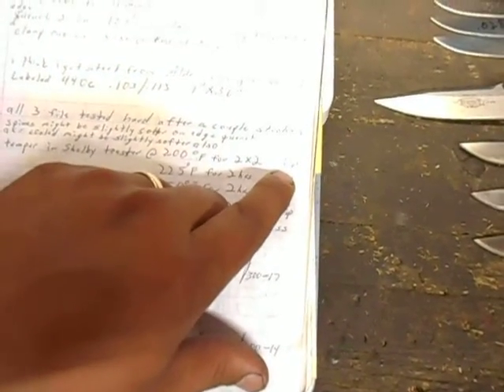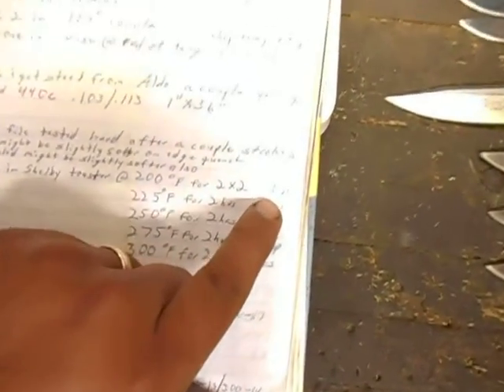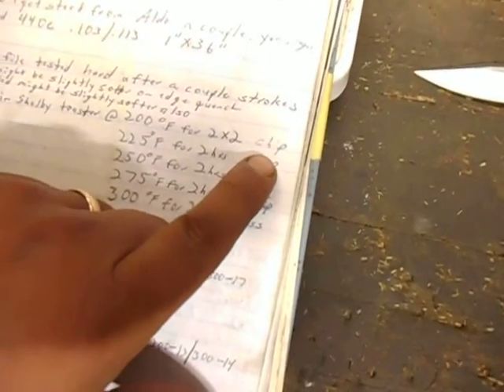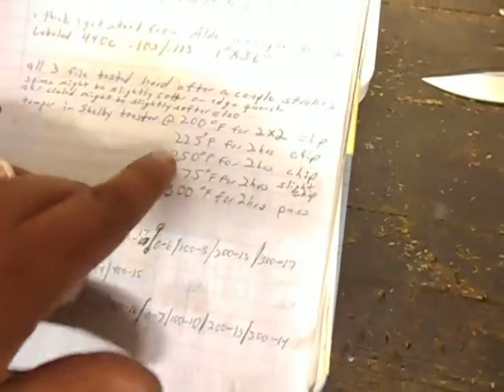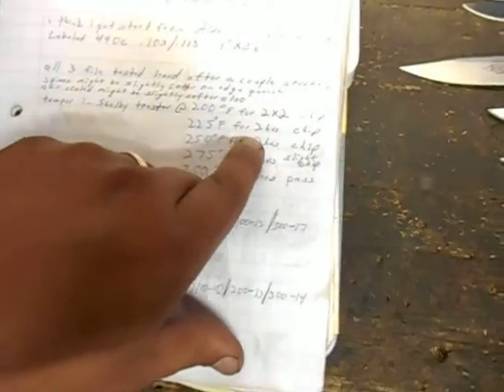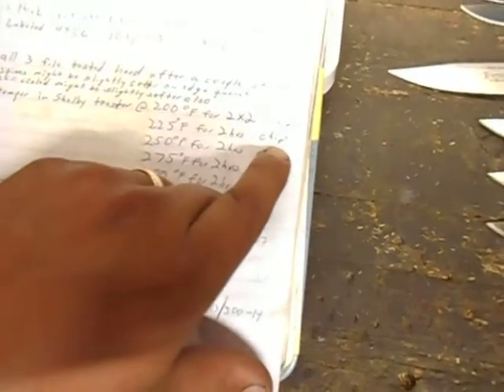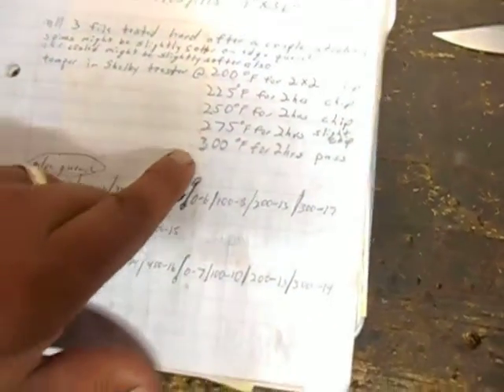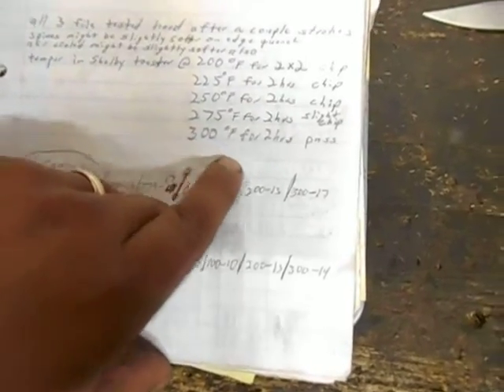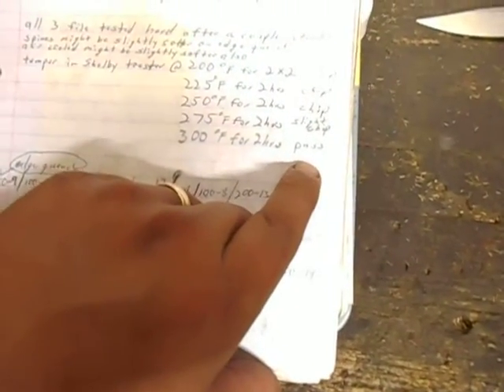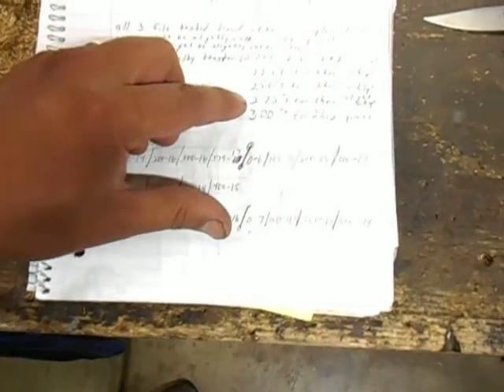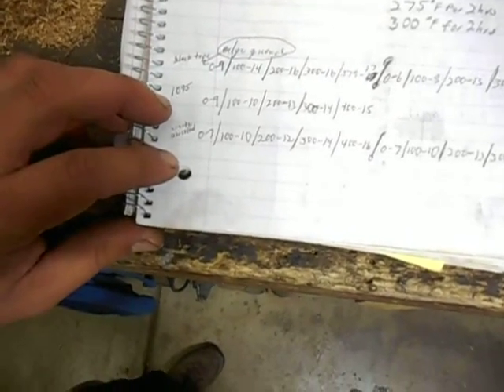then tested it on the brass rod, and I got a chip. It chipped really bad. So I upped the temperature 25 degrees for another 2 hours, tested it on the edge flex test, it chipped, came all the way up to 300 degrees for 2 hours, and they passed. No chipping. Once I got a usable edge at that point, then I went ahead and did some cut testing.